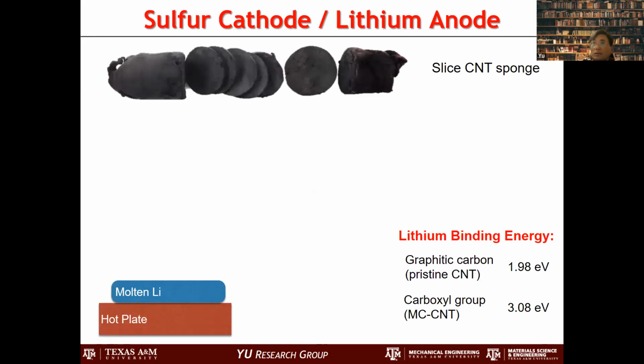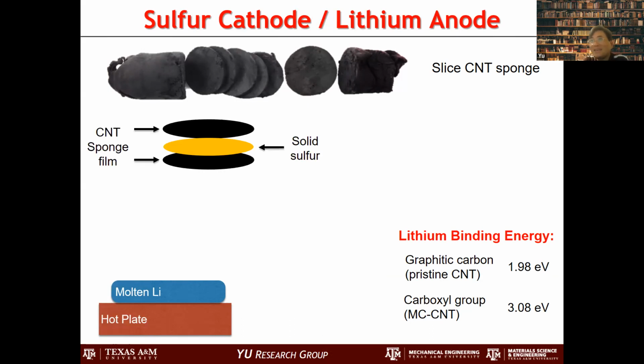And another thing that we are working on is we actually use this as a lithium anode, and we slice it. We slice this actually here, and these days my students can slice it about 100 micron thick. Actually, they are doing this pretty well. Using the razor blade, they can cut, and nothing is required other than the razor blade. And they're actually doing pretty well. Now it's slicing it, and we actually put the solid sulfur in between, and this is a cathode, and we press it, make a cathode.